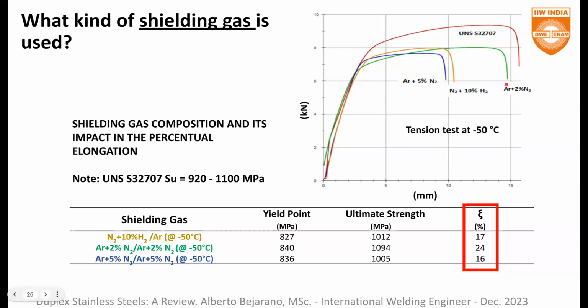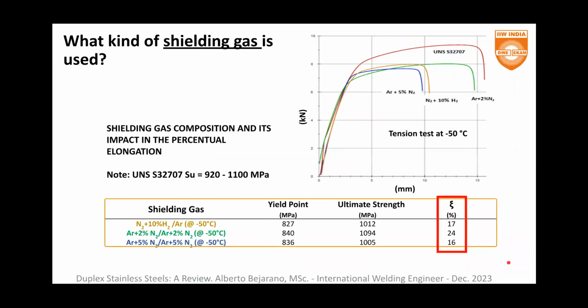If you see here, even the percentual elongation is related to the shielding gas that you are using. Imagine that with 2% nitrogen, you obtain 24% elongation, and only 16% with 5% nitrogen. That is pretty amazing, because the difference is only 3% of nitrogen. Okay, pretty good. I hope you are following me.